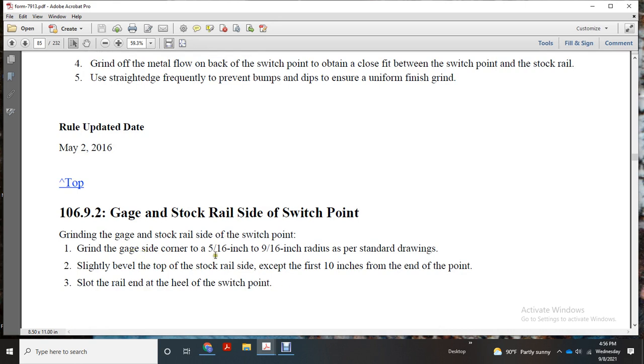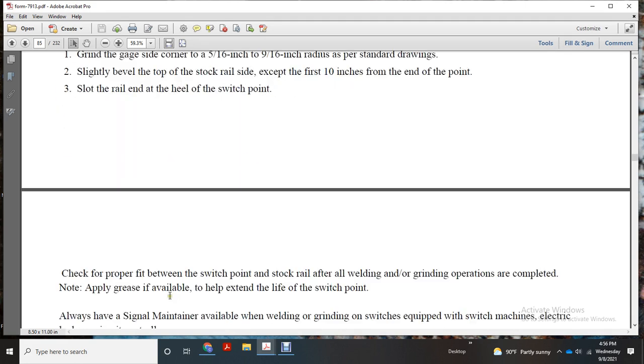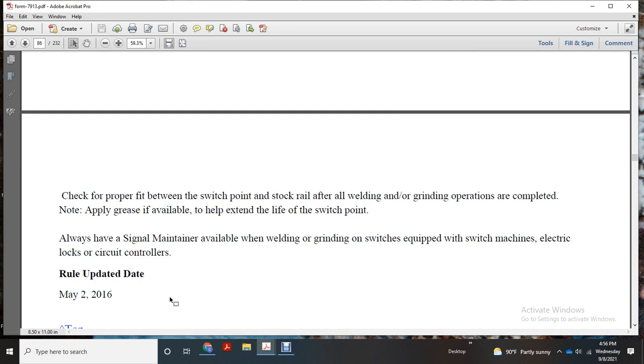Grind the gauge corner 5/16 to 9/16 radius per standard drawing. Slightly bevel the top of the stock rail side except the first 10 inches from the end of the point. Slot the rail end at the heel of the switch point. Check for the proper fit between the switch point and the stock rail.